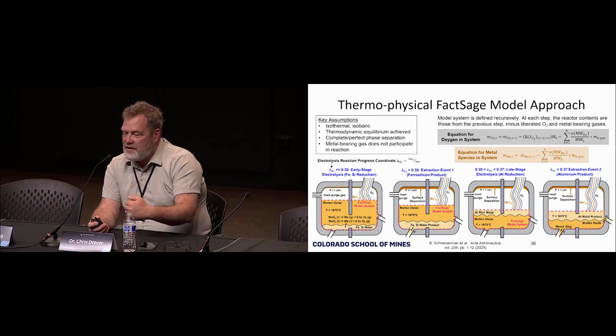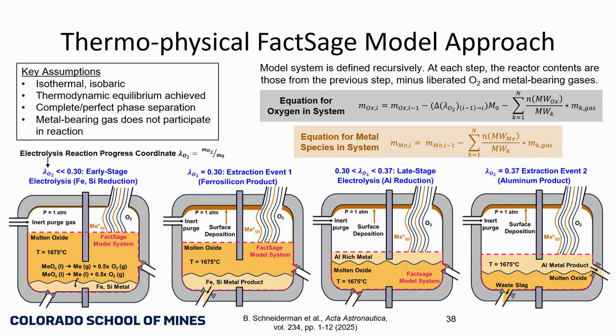And in this system, we're working with a Highlands simulant. We begin by extracting iron and silicon. Then we reach a point we call the transfer point, where we would extract the iron silicon, and then electrolysis continues, but this is primarily on aluminum. With the aluminum then being a lighter metal, it floats on top of the melt. As iron silicon's heavier, it sits beneath the melt. And then we extract that off. And this study on the thermal physics has guided us on the likely composition of the produced aluminum, as well as the iron silicon mixture, and other factors to be considered.